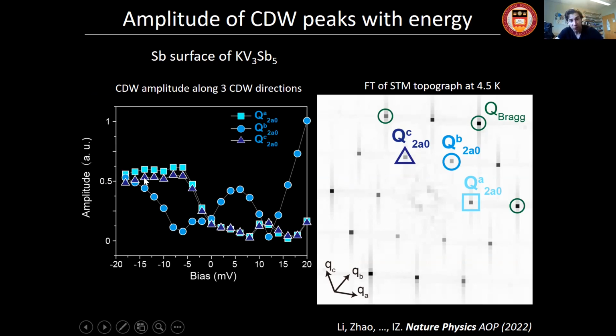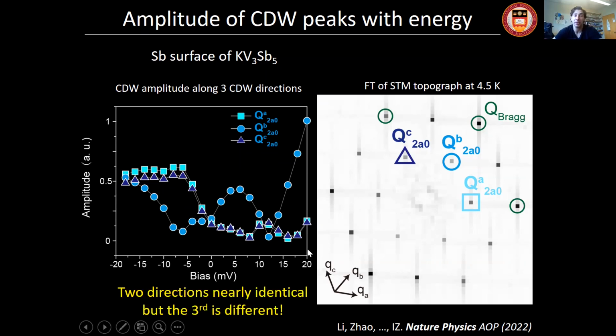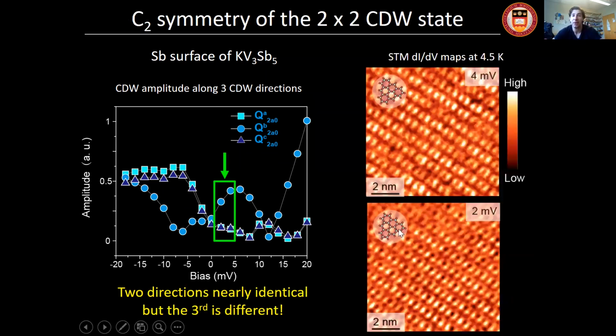What you will see is that for two of these symbols, the squares and the triangles, the intensity profile is nearly the same. But for the third one, it's clearly different. It's almost opposite: if you have a peak here for QB, it's a trough for the other two, and so on. We're still working to understand the underlying physical mechanism behind these differences in intensity as a function of energy. But in any case, this clearly demonstrates a preferential direction where one CDW wave vector is different from the other two. This is again consistent with a C2 symmetric state that we had before.